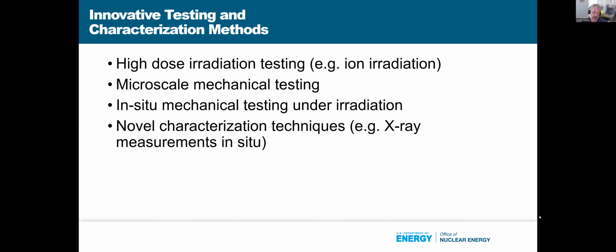But I would just say that I completely agree with you that being able to standardize these small scale techniques to show that they provide data that links to large scale testing is critical in these different measurements. So, whether it's making sure that you're testing across enough grains, or making sure that the orientation so that you can correlate that measurement with the grain orientation. All of those have to be looked at depending on what the size and scale is, because some of these micro scale techniques cover a lot of area. Micro scale could be 1 to 2 micron with FIB'd out specimens, or it could be 100 micron femtosecond laser cut specimen.